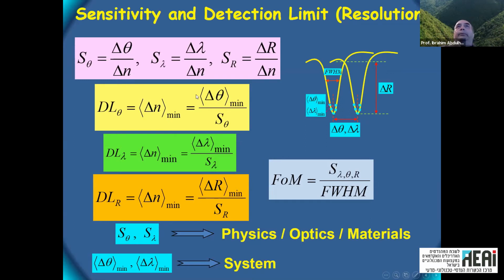So if we have the minimum value of the angular shift, let's say delta theta minimum, or wavelength delta lambda minimum, like the resolution of a spectrometer, we divide by the sensitivity, because the sensitivity is defined by this shift versus the change in the refractive index. So if we take delta theta minimum here, it will be delta N minimum here, which means the detection limit is determined by the signal when it becomes roughly comparable to the noise. So when we have signal to noise ratio almost 1.